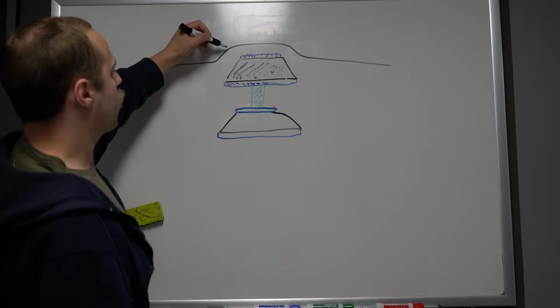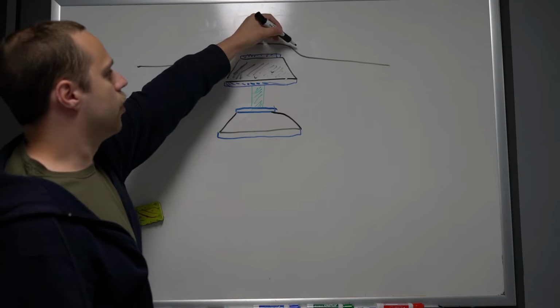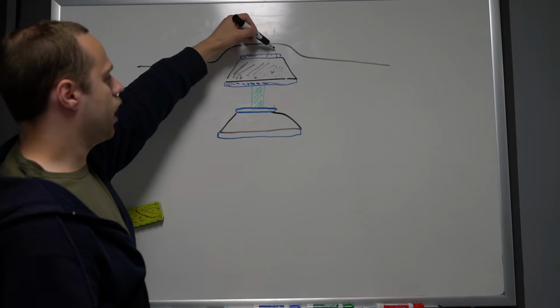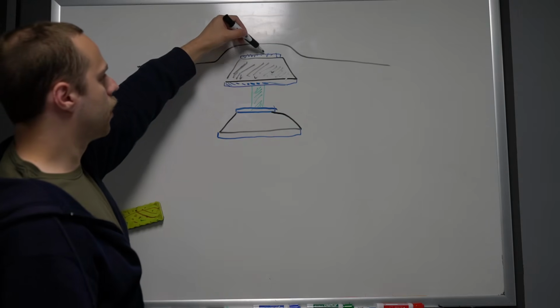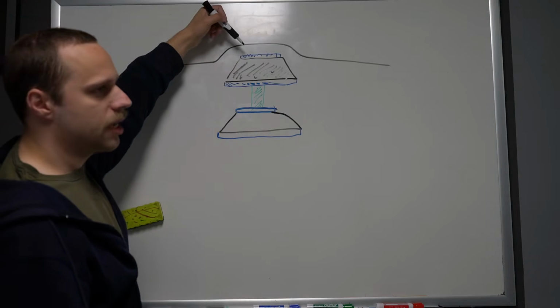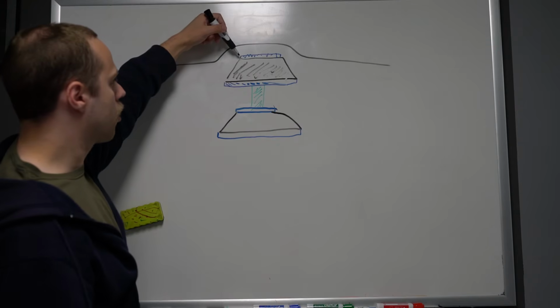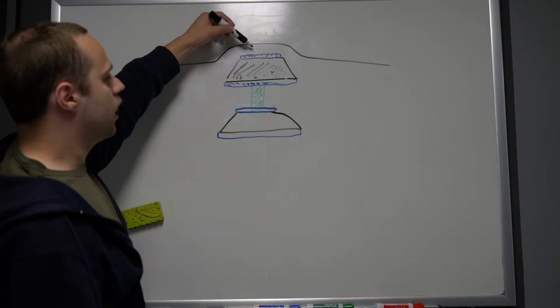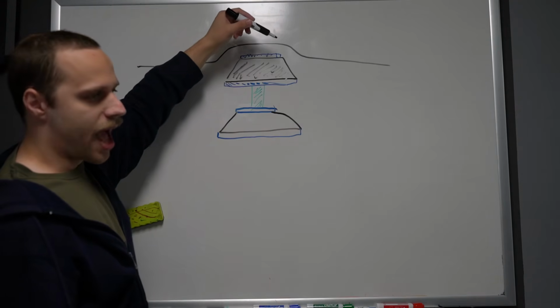And so as we start wet etching in from the top, we're going to hit this top layer, which again is probably titanium nitride or something along those lines, and that is relatively resistant to attack by the HF.